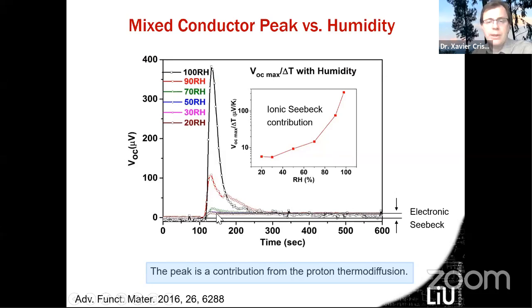So this is an interesting feature, because what you have is a material where, if you know the Seebeck coefficient, you would just measure the voltage you obtain, and then you can know the temperature gradient. At the same time, if you measure the peak here, you can know the humidity. So you can both read the humidity level at the peak value and the temperature gradient at the plateau value. This is an interesting material where you can access two parameters, temperature and humidity, with a single material.